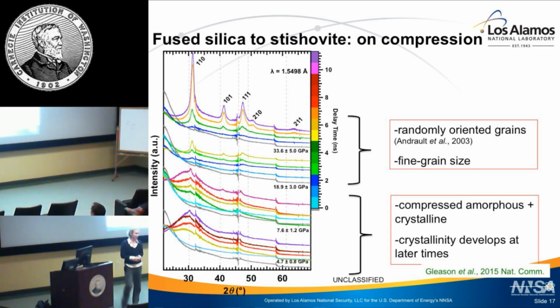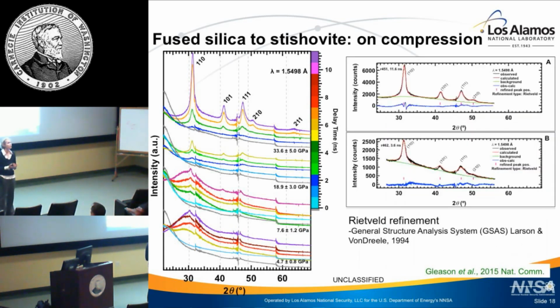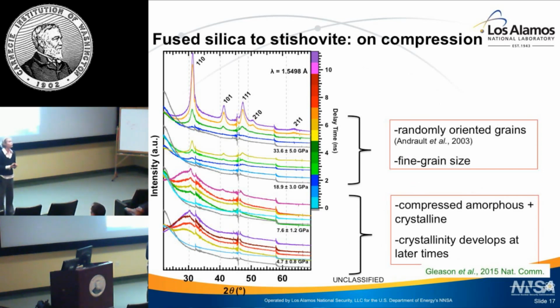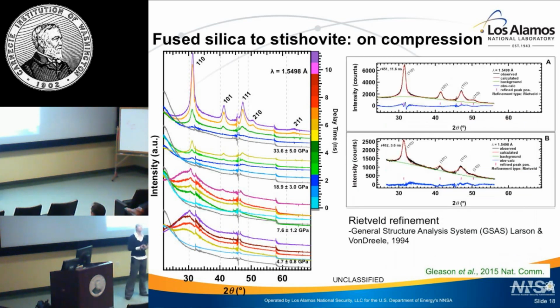In fact, X-ray free electron laser based diffraction coupled with shock compression has really provided the first opportunity for shock physicists to perform Rietveld refinements on their data sets, right? So this is really revolutionary in that you can begin to pull out phase fraction information. And this is a very powerful technique.